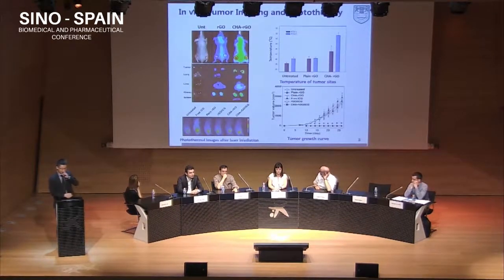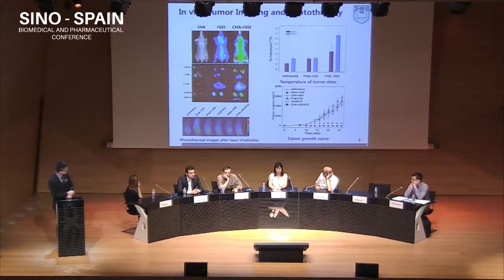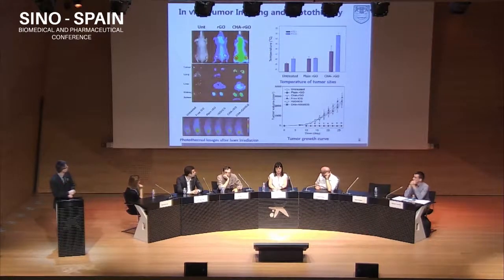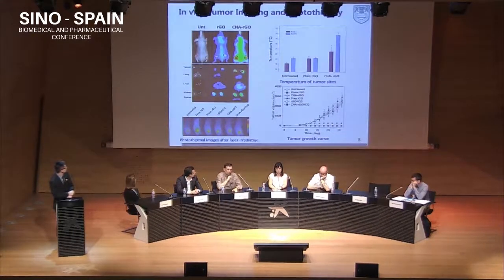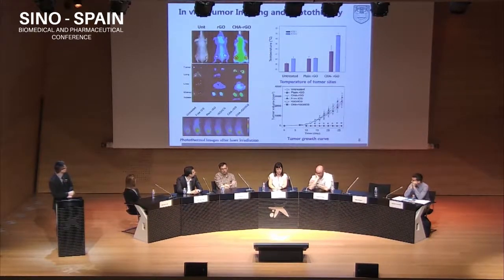We also constructed a tumor model in mice, and after intravenous injection of the CHA-RGO loaded ICG, we found a very strong accumulation of our nanoparticle system in the tumor tissue. In the ex vivo study, we found in the tumor region the intensity is 4-fold higher than the non-active targeting systems. Also, in the tumor tissue, the intensity is higher than in the liver and the kidney.